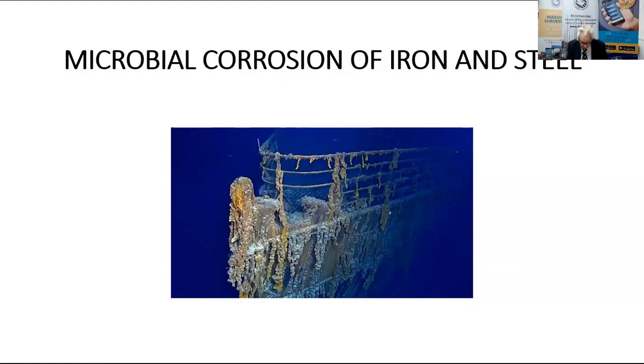It's pertinent to know that when a sample of the steel from the wreck's double bottom was brought to the surface, it was found to contain over twice the amount of sulphur that the classification societies allow for class ships these days. For a ship to be classed, the sulphur content of the steel must be less than 0.03%, which is very low. The Titanic, it was 0.067%.